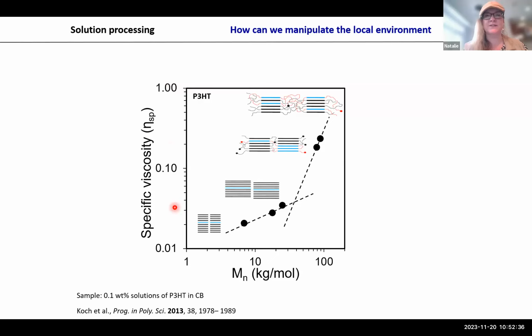Clearly, again, when we have polymer-polymer blends, rather than just random mixing, we first learn a bit about the system. And we usually start with viscosity measurements. So Henry is here. It's pretty simple. We have a viscometer, and we do that for P3HT and PVDF. And we change the molecular weight, again another reason to have P3HT, and see how the viscosity in 0.1 weight% solutions in chlorobenzene changes.